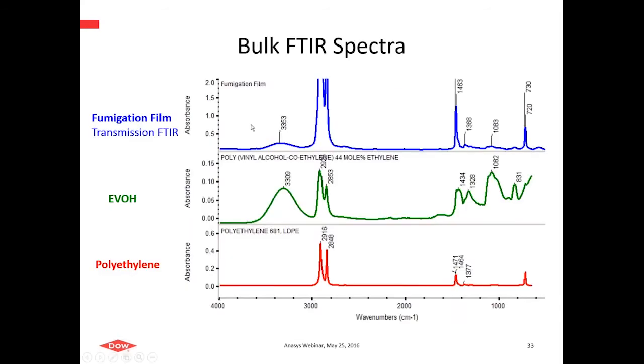Before I get to that, let's just look at the spectra. So we start, again, I mentioned bulk. In a bulk sense, we would do whole film transmission, and then these are now representative FTIR bulk spectra of both polyethylene and EVOH. And we can see that this fumigation film is really just a combination of these two materials. All of the spectral features are accounted for by just combining these two materials.